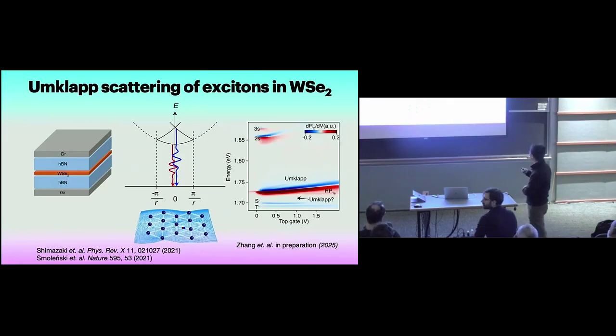So in principle, we can look at the line width of this repulsive polaron, and we actually look at it. You have to be a little bit careful of how you extract the line width, because it's a very small feature. So we developed some technique, actually shown in the previous paper. We need to do very careful fitting to extract that line width. So indeed, there could be some variation across different spots. Of course, we only probe diffraction limited spots, so we cannot probe the domain sizes of the Wigner crystal, which are typically smaller than your diffraction limit. Yeah.